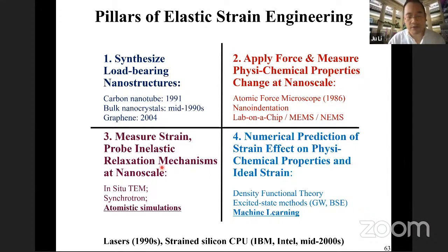And also, let's say you want to have a piece of germanium at 70 Celsius under 6% strain for 3 years, so you can use it in your cell phone, but after 5 months, you found that strain is gone. You want to know what's the reason for the inelastic relaxation. Was that dislocation nucleation from the surface? Was that diffusional creep? Was that fracture?